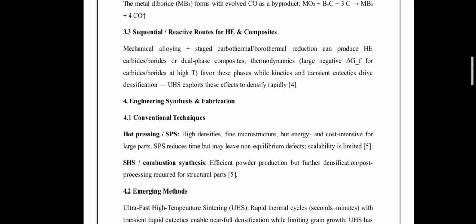First are the conventional processing techniques, hot pressing and spark plasma sintering. Hot pressing and spark plasma sintering are the most established densification routes for ultra high temperature ceramics. Both methods apply simultaneous pressure and high temperature, enabling high relative densities and fine microstructure. Spark plasma sintering significantly reduces the processing time due to rapid Joule heating and enhanced diffusion. However, it is energy intensive, expensive, and suffers from limited scalability for large or complex components. In addition, the rapid heating can introduce non-equilibrium defects which may affect high temperature stability.